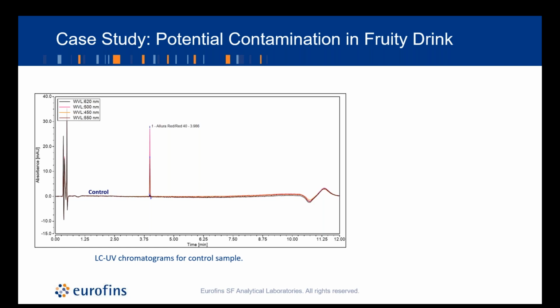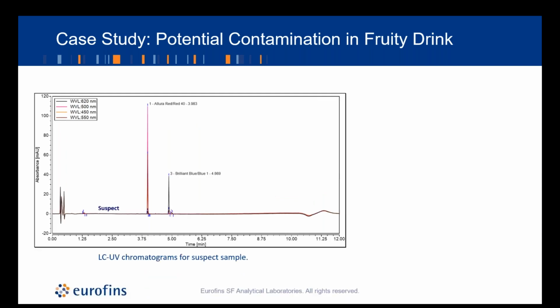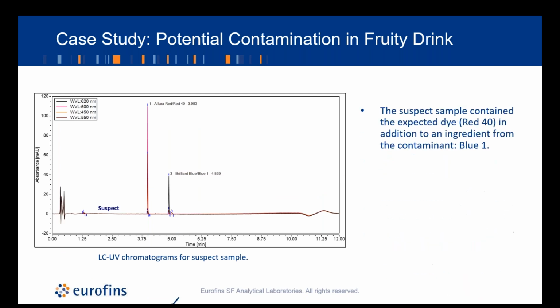So this is our control sample profile, and we see a nice peak here for Allura red, which is red 40, which is what we expect for the product. And this is our suspect sample. So we still see our expected peak, red 40, but we also see another peak here for brilliant blue, which is blue 1.